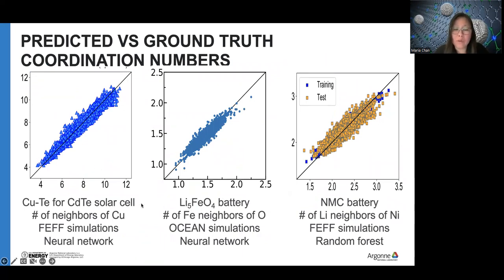So the three examples are shown here: cadmium telluride solar cells, copper as a dopant, the number of nearest neighbors for copper; lithium iron oxide battery, the number of iron neighbors for oxygen; and NMC batteries, the number of lithium neighbors for transition metals. You can see that we use different simulation codes, balancing accuracy and cost, and different machine learning approaches. The results are actually really similar. We find reasonable accuracy, maybe 5% in coordination number, maybe 8% sometimes. The machine learning approach actually didn't make a huge difference.